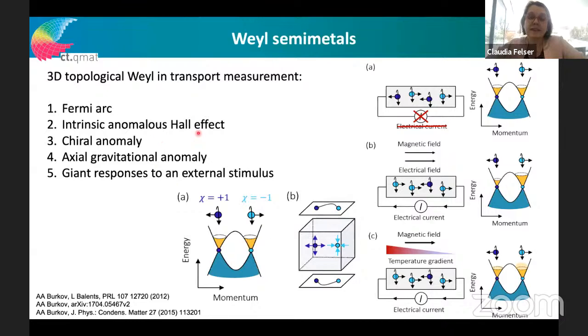The next thing is then we investigate the intrinsic anomalous Hall effect and the chiral anomaly, and this is done by electrical transport. We apply a magnetic field parallel to the electric field. In a normal Hall measurement, we see a different property compared to when we apply the magnetic field parallel to the electric field. So we see the so-called chiral anomaly, which is a negative magnetoresistance effect in this material. This is more or less a smoking gun experiment, related to an extra contribution to the Maxwell equations in this Weyl semimetal.